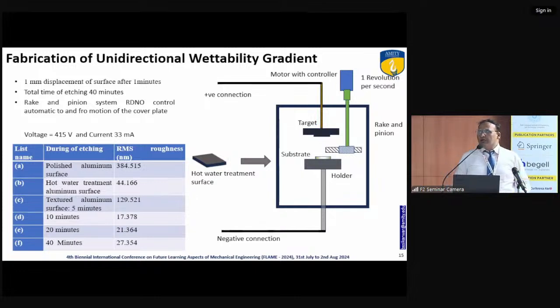So now how can we produce a unidirectional wettability gradient? What do we have to alter here? This is the holder, and this is the cover on the substrate, and this is the target area, and here we provide the motor. This motor is rotated to move the cover slowly away from the surface. So it is exposed, where ions are coming and striking the surface. In this way, we measure the contact angle and roughness. This is the order of roughness we can get here.